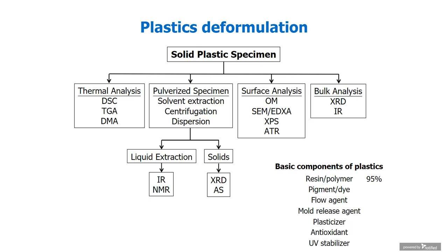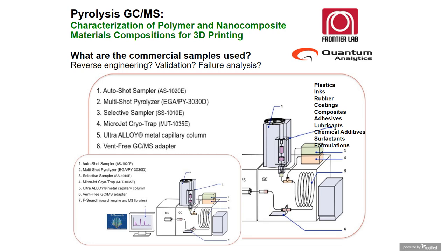Now, this is not hard to demystify if you know your plastic chemistry. The resin or the polymer is basically the major component. So if we're talking about polyesters, polyurethane, that will be the major component. However, in processing, many additives are included, which would be your dye, your flow agents, mold release agent. That is the harder part, which is demystifying or deconstructing the remaining 5 to 1% of your plastic component.